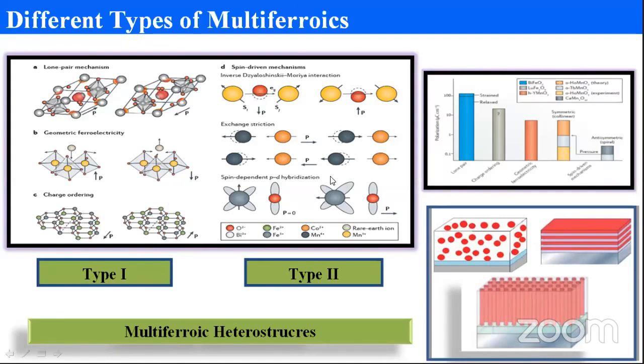Okay, so the multiferroics can be classified into different classes for single phase materials. Okay, but I'm going to take only this material, bismuth ferrite, lone pair mechanism, because you can see here this has almost 90 microcoulomb per centimeter square, which is one of the huge electric polarizations, one of the best materials for ferroelectric polarization. Okay, but throughout this presentation, I'm going to concentrate on these heterostructures, multiferroic heterostructures, and on this also.